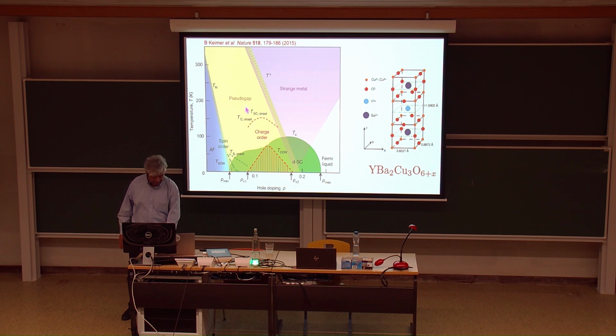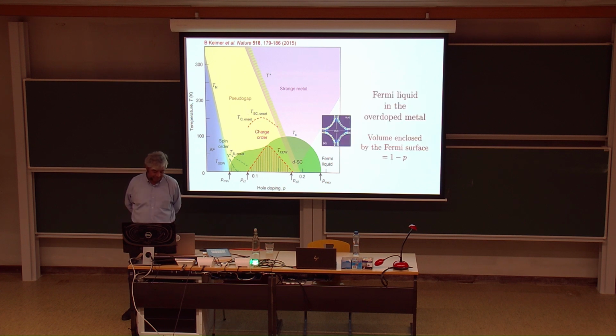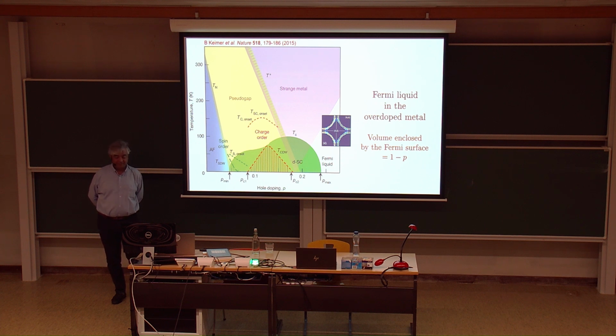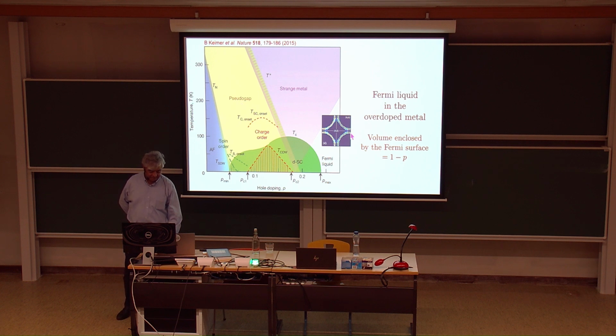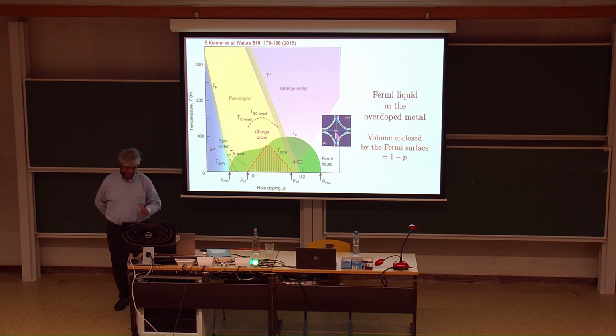But before I get to the pseudogap, let's talk about what happens at very large doping. So at this point, you do get a familiar state, the Fermi liquid. And one way you can see that is by looking at the Fermi surface. So this is a photoemission observation of the Fermi surface, the locus of zero energy fermionic excitations. And Fermi liquid theory says that the volume enclosed by the Fermi surface, which is this region here, should be equal to the density of electrons. And indeed, that works out. And many other things about the Fermi liquid also work quite reasonably.